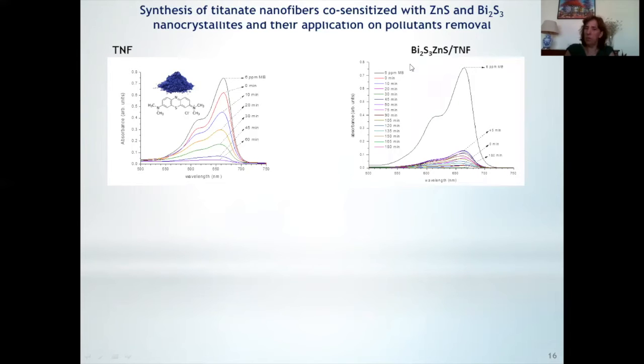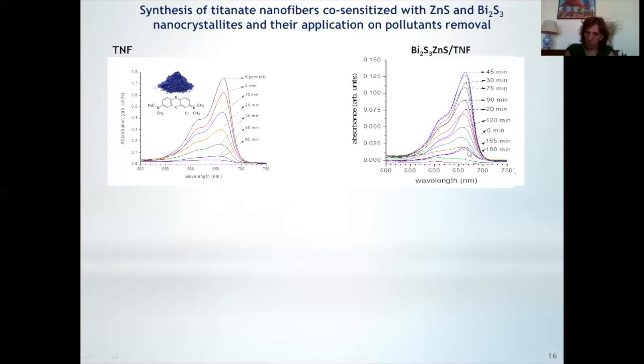But if we look at the same experiment, but using bismuth sulfide and zinc sulfide, what do we see? We have our solution, and then we put this solution in contact with our material, and then we turn on the lamp. And when we turn on the lamp, our absorption was here. So all of this was absorbed in our material. To see the situation better, look, we are here when we turn on the lamp, and then follow me: 0, 20, 30, 45, 75, and so on. And now we are here at 3 hours, okay? So what happened here? Because when I start the radiation, I also start to increase the amount of dye that I have in solution.